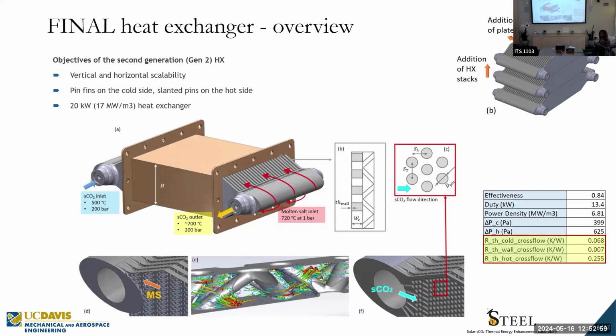Is there a pump that pumps this molten salt? Since we haven't had the loop to interact with, I don't know. There is no functioning chloride salt loop in the US, let's put it that way. Oak Ridge was given money, they put a loop together, but they ran out of money to test, and then they changed pathways. So we work with NREL. NREL has corrosion test facilities, but these are static corrosion tests. We print additively manufactured samples, and they have a test cell with the same salt, and they dip it in there to see what the corrosion rate is. So there are different aspects to this.